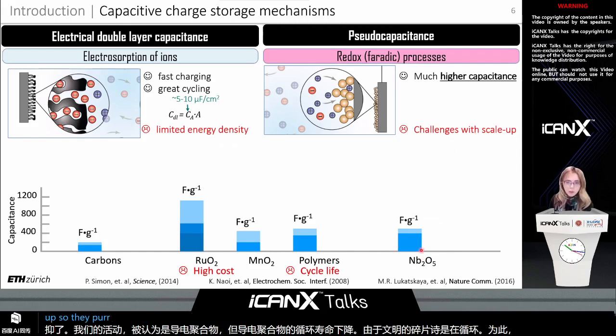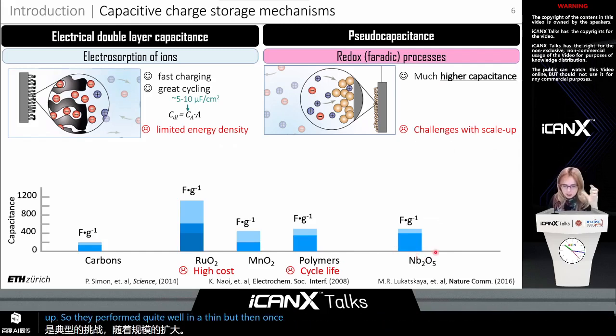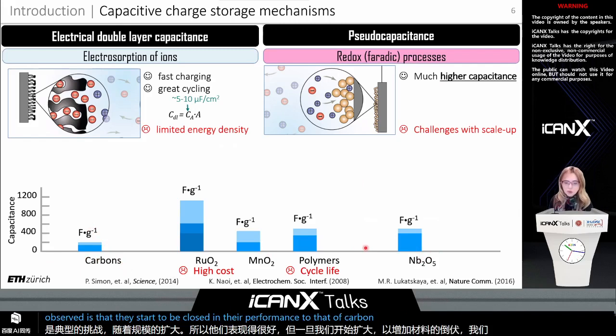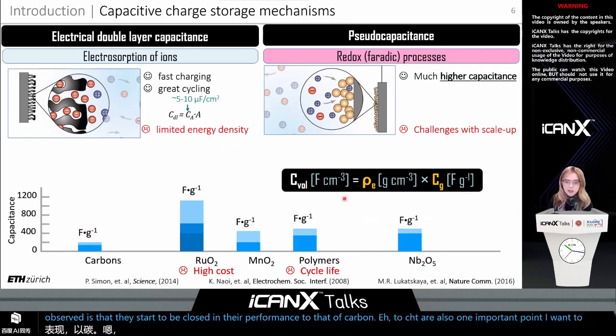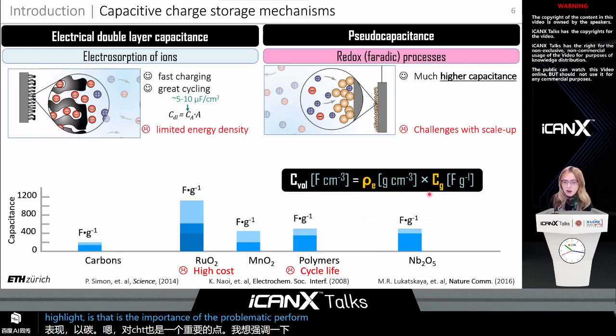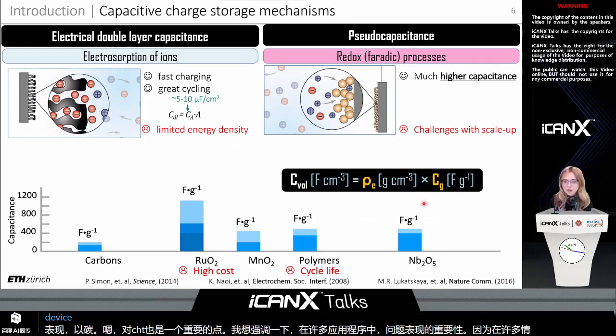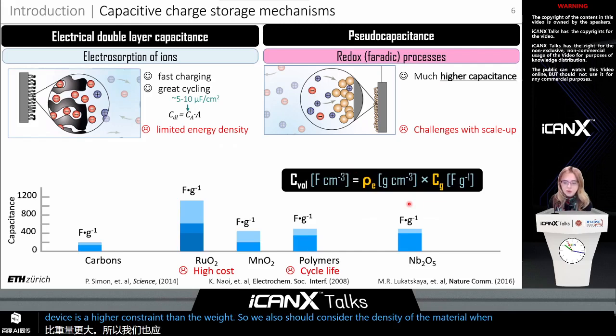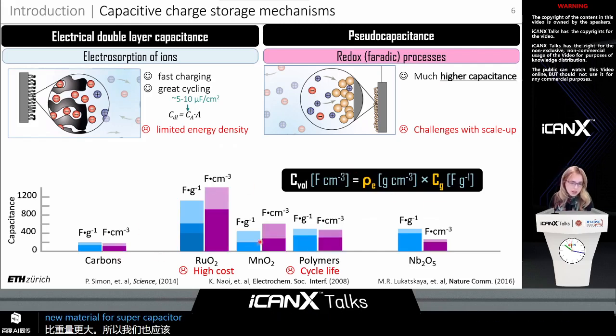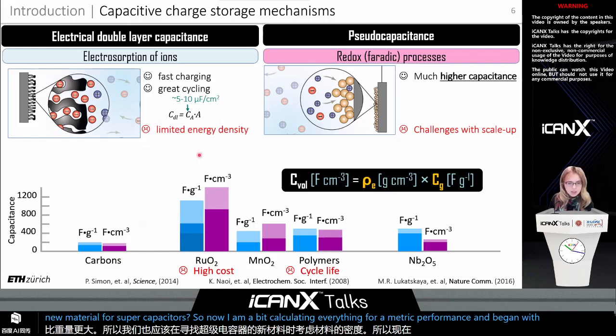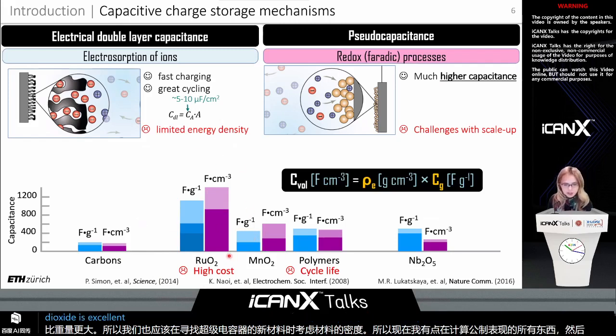So they perform quite well in a thin electrode, but once we start to scale up or increase the loading of the material, what we observe is that their performance starts to be close to that of carbon electrodes. Also, one important point that I want to highlight is the importance of volumetric performance in many applications, because in many cases, the volume of the device is a higher constraint than the weight. So we also should consider the density of the material when we are searching for a new material for supercapacitors. So now I am recalculating everything for volumetric performance. And again, we see that ruthenium dioxide is excellent, but unfortunately is expensive.